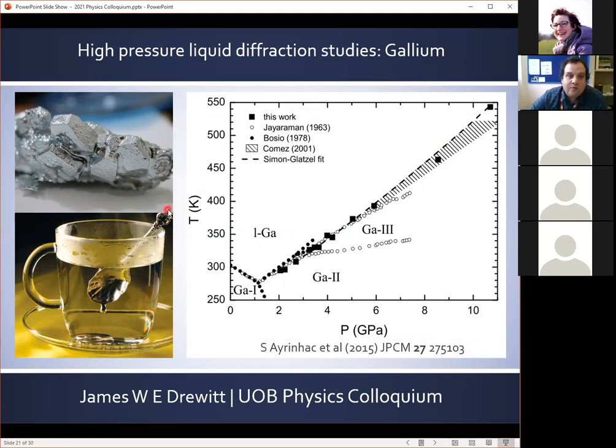So gallium's a remarkable metal. At room temperature, it crystallizes into a complex orthorhombic structure with mixed metallic and covalent bonding. And this gives rise to some unusual characteristics, including its anomalously low melting point. So metallic gallium will melt in your hand or in your tea. And the implications of this means it has one of the largest liquid stability ranges of all the elements, and similar to water, undergoes a 3% volume expansion on solidification. And so it also has this negative melting curve initially.